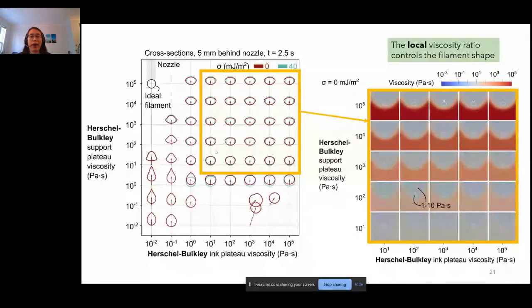So we can identify why that happens by looking at slices of our simulation. So here I've sliced through the bath, and the color is indicating the viscosity of the fluid. So in the center of these plots, you can see there's this sort of white outline. That's the outline of the filament. So inside the filament, the viscosity is about 1 to 10 Pascal seconds for all of these. And then there's a yielded zone outside of the filament where the support is at about 1 to 10 Pascal seconds. And then outside of that yielded zone, all of these supports are at a different viscosity, which is their plateau viscosity. So because we have the same viscosities within the yielded zone locally, that means we have the same local viscosity ratio for all of these plots, and that's why we get the same filament shape. So we learned here that the local viscosity ratio is what controls the filament shape.